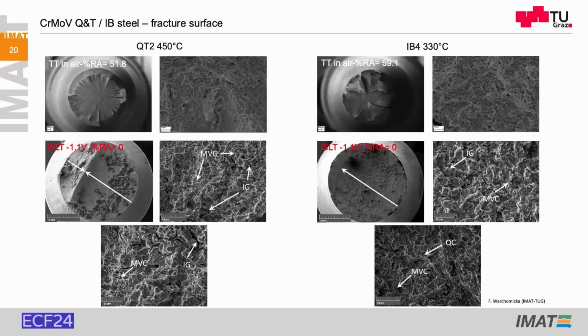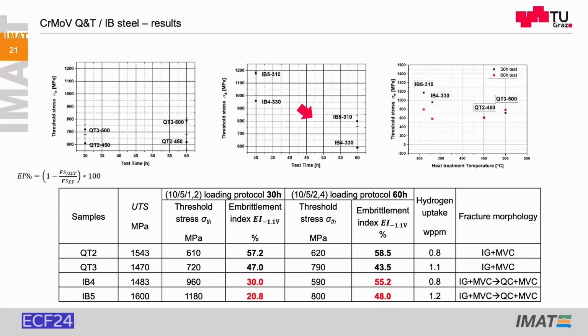And the fracture is intergranular microvoid coalescence for the quenched and tempered, as well as intergranular and quasi cleavage for the austempered microstructures. Yeah, this is the result. Here again, if we make loading for a longer protocol of 60 hours, the hydrogen index is increasing.